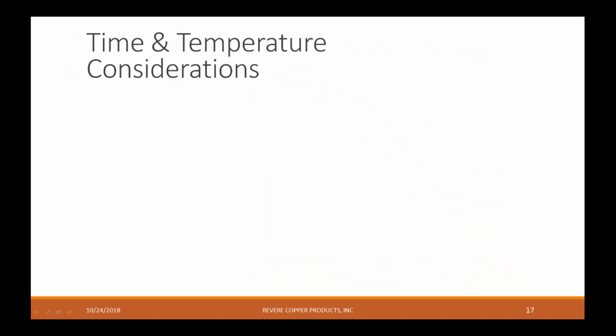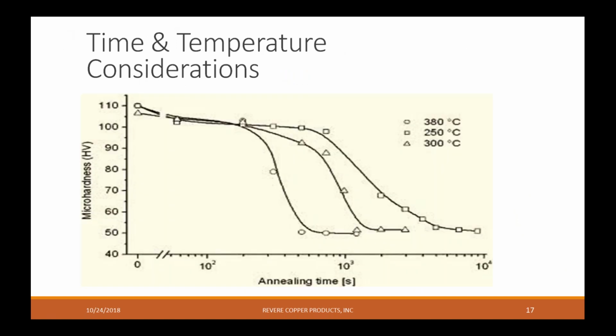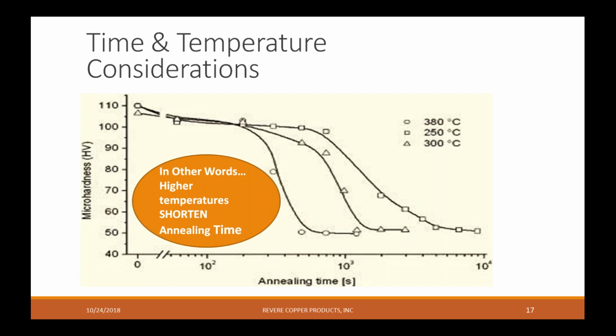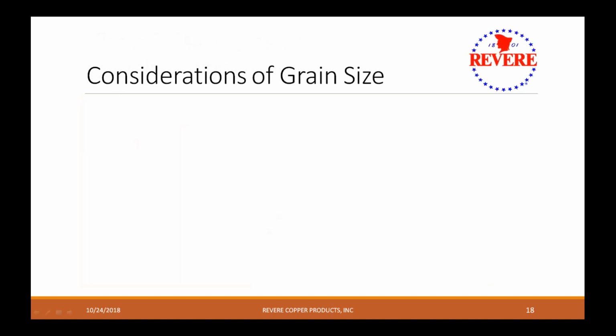So this next slide shows a little bit about time considerations with annealing. So you can go with a lower temperature and a longer time. Basically, higher temperatures shorten anneal time, or lower temperatures, you have to go for a longer time. And that's for grain growth. So if you were going to order soft metal, what would you see from different grains? So some considerations of grain size.